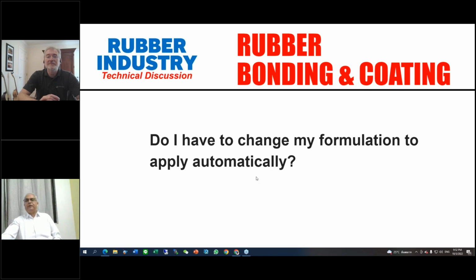Now, Mike, I got, in relation to this one particular point, many times the manufacturer defines the formulation type, but we do not follow that and face the problems we have been talking about. So you rightly mentioned, Mike, that without changing my formulation, by appropriate addition, I'm able to achieve the desired quality. Many times people do ask, I'm using maybe 60% solvent and 40% adhesive. The solid content is a very important and prominent parameter which we are neglecting.